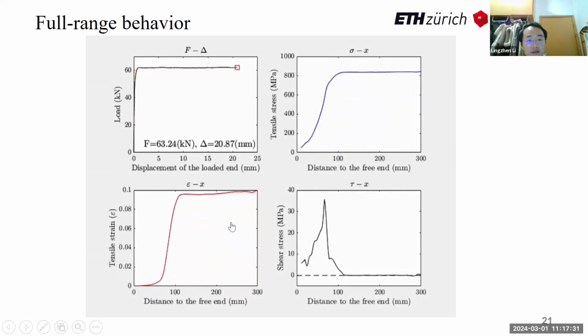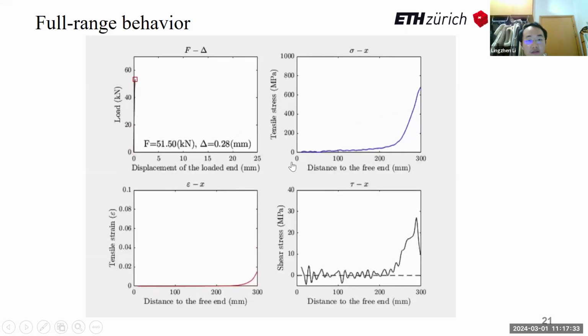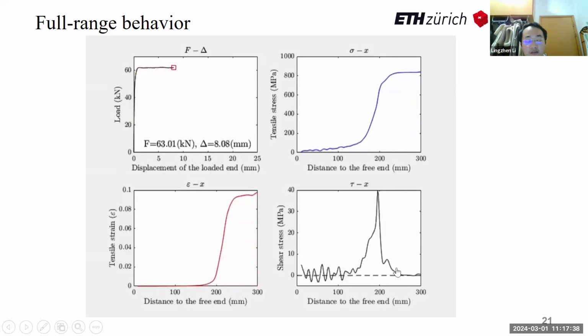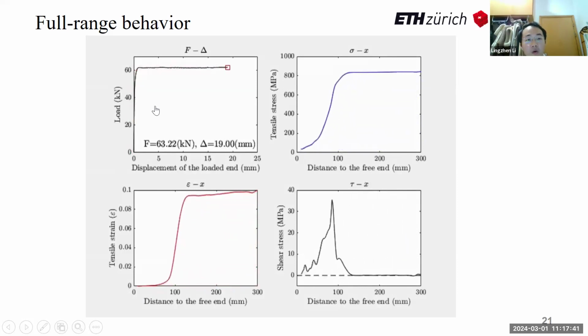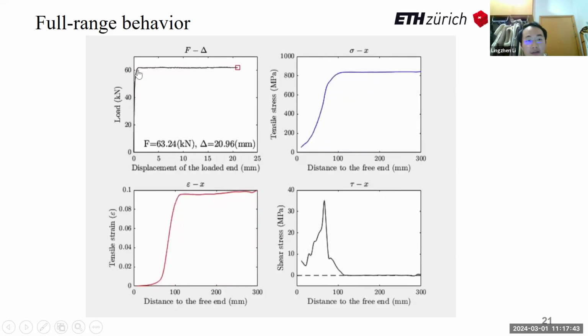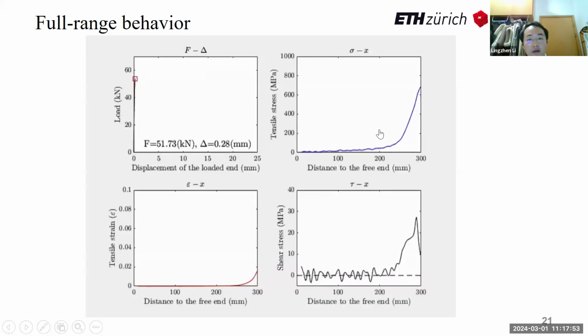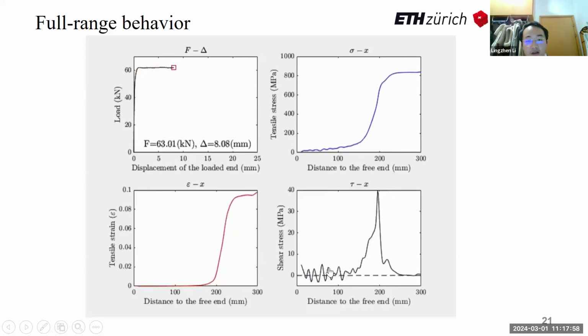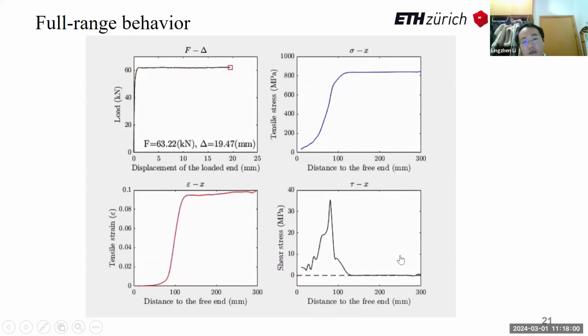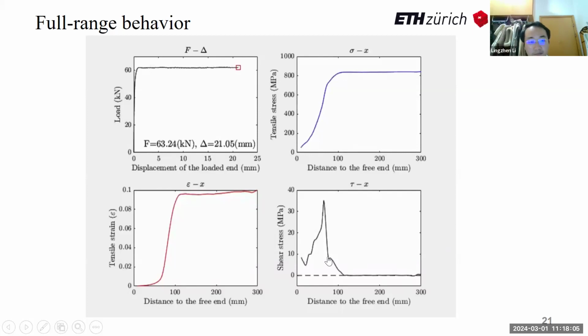As the force increases, the tensile stress and tensile strain of the shape memory alloy, and also the shear stress in the adhesive bond, increase. But once the force enters the plateau, which means the bond capacity is reached and damage happens in the adhesive line, the tensile stress profile, tensile strain profile, and shear stress profile didn't change shape, but propagated from the loaded end to the free end.